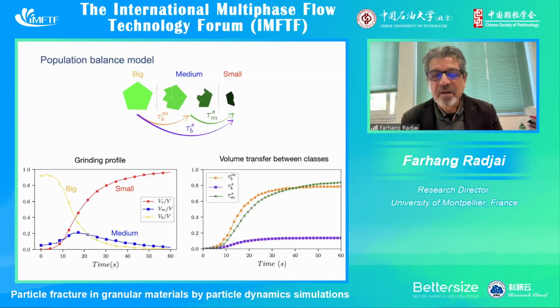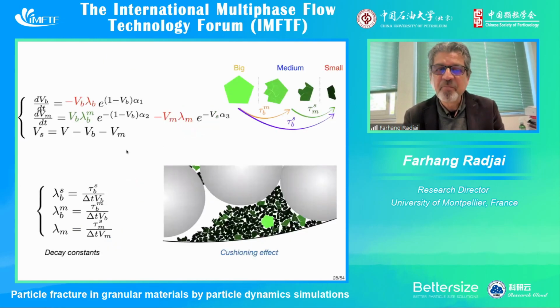We also studied the evolution of, we have this population balance model, which is also a statistical approach to the grinding problem, in which we look at evolution of different classes of particle sizes. So we divided the sizes of the particles into 3 classes. And we looked at the rates of transition between these different classes. As you can see here, you have the evolution of the average sizes of the particles of these 3 classes. And here we have the rates, which have been evaluated from simulation. We show that we can model these rates by using these functions that you can see here.